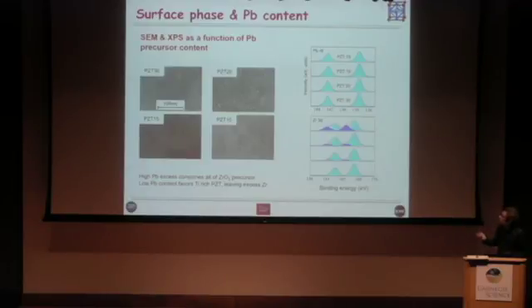You can see this in the XPS. The lead core levels don't change. That means that the lead chemical state and local environment is always the same, whatever the lead excess level we use. However, this is not the case for the zirconium. For the 10%, there are clearly two environments. One is that associated with PZT, and the other one is at higher energy. And as we're going to see, it is associated with these nanostructures, which are more like zirconium oxide. This second component decreases with increasing lead precursor excess, and effectively at 30%, there are no more nanostructures, and this second high binding energy component has disappeared.